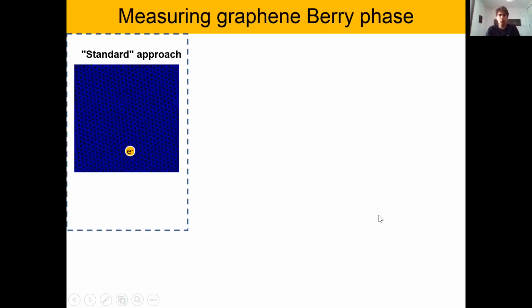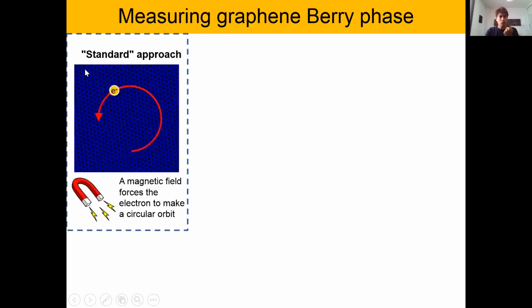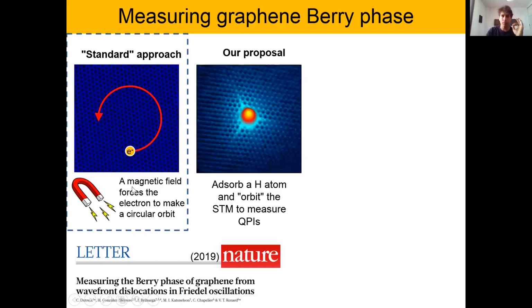So let's go to our approach. I am not claiming that we are the first, of course, to measure the Berry phase of graphene. I'm just showing here a new way of measuring it without the need of a magnetic field. As I told you, the Berry phase is the phase that an electron accumulates if you make a closed adiabatic trajectory. The standard approach is to apply a perpendicular magnetic field, and then you have the cyclotron orbit where the electron makes this closed trajectory, and it might accumulate a phase, and you can probe whether it has done so by applying perpendicular magnetic fields. So this is the general belief, that you need to apply these magnetic fields, but we saw that it is not necessary. You can apply a trick.